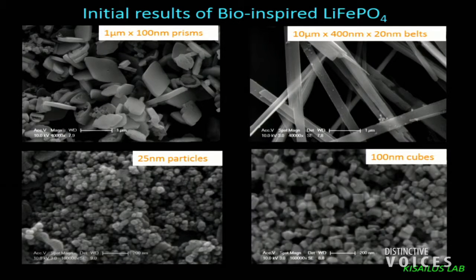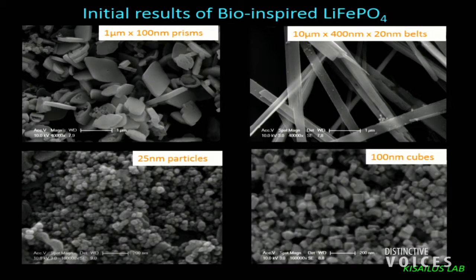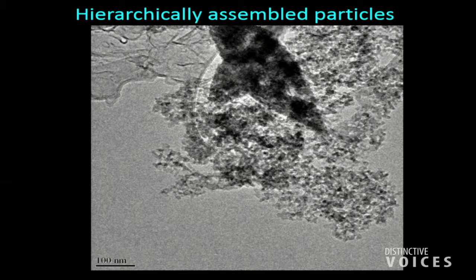I'm going to skip the next few slides, but essentially we're making the same materials that are in the lithium-ion battery. If you looked inside the Chevy Volt, the cathode particle is about 5 micrometers, a spherical structure, about 1/20th the thickness of a human hair. That's boulders in our world. So we want to make materials, for example, this nano belt that's 20 nanometers thick. That's significantly thinner than 5 microns, where the lithium ions can go in and out and get into that structure faster. So we do this using bio-inspired processing.